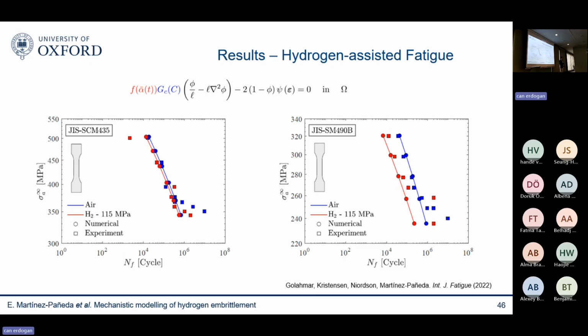And we have also extended this to fatigue. There's a growing area of phase-field fatigue, where the idea is that you have a fatigue degradation function. So not only do you degrade the toughness of your material through hydrogen, but you have a variable that accumulates with your cyclic loading that degrades your fracture toughness. The price to pay is that you need to add 2 parameters to your model that quantify how susceptible your material is to cyclic load, basically to cyclic damage. And when you do that, we can capture SN curves with and without hydrogen with, I would say, relatively good agreement.